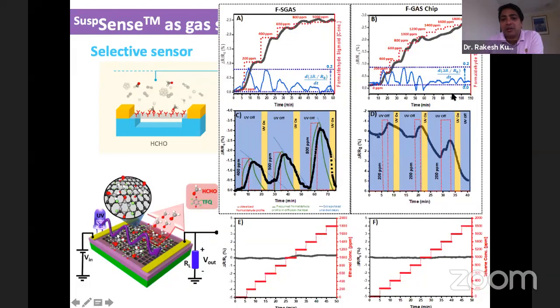What do you see on the plots on the right? Plot A is for varying concentrations of formaldehyde: the signal from the sensor changes quickly, and it responds quickly to the change in concentration. B is a graph for graphene not suspended, but supported on a surface. As I mentioned, graphene is a single atom thick. As soon as you lay it down on a surface, the surface-based imperfections start diluting the pristine properties of graphene. But when it's surface-free graphene, you maintain all the pristine properties in suspended graphene structures.